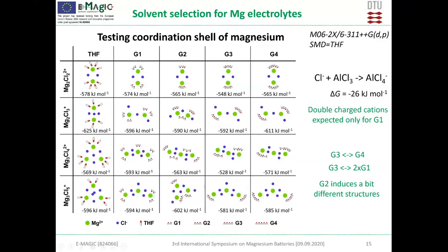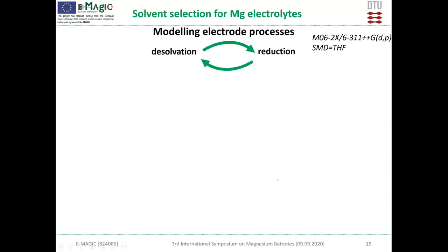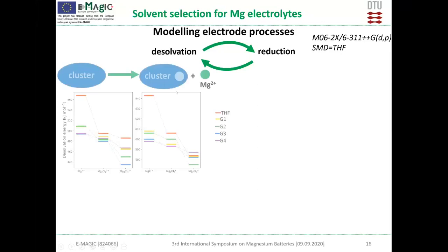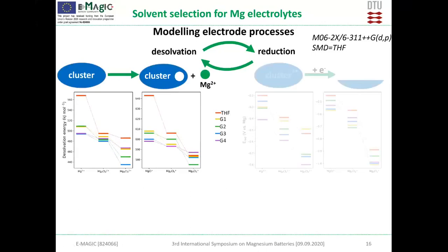But the most important is to see what is the connection between these structures that we generated, that we think are most stable, and the electrode process. At the electrode, we have 2 processes that are happening: desolvation and reduction. These 2 processes are overlapping, but in calculations, it's very difficult to make it at the same time. We can do a calculation for desolvation, just removing magnesium, and also a calculation for reduction, adding 1 electron to the system.